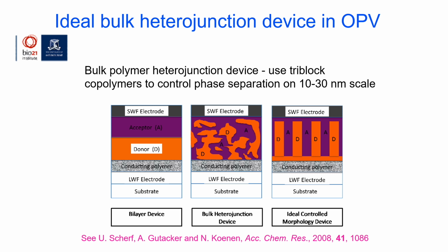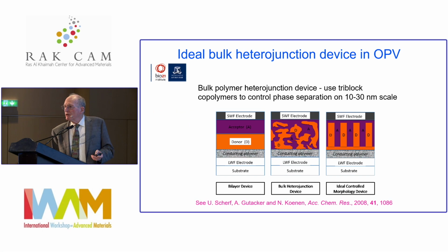They survive longer if there's good supramolecular order and good mobility, so they can get to the interface. But the planar interface, as shown here, is not particularly good at providing a maximum number of opportunities for charge separation. And so people always thought that the best thing was to have an interpenetrating network of donor and acceptor materials, so you were increasing the chance of an excited state being able to migrate on this 10 to 30 nanometer scale to an interface where charge separation was assisted by the difference in the HOMO-LUMO gaps of the two materials. And that can also be perhaps more ordered by having a pillared structure like here.